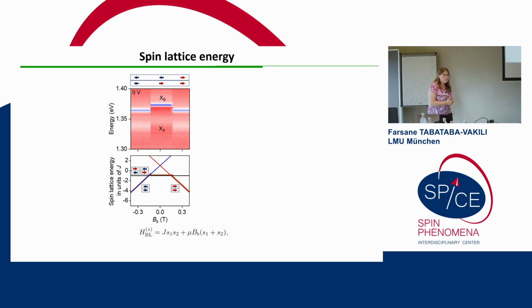And now let's have a look at the spin lattice energy to get a better understanding of when which spin flip occurs. So in the bilayer, the situation is relatively simple. We have two antiferromagnetic states which are energetically degenerate and two ferromagnetic states. If we now start off at a negative magnetic field and increase the magnetic field, we start off in the ferromagnetic state, we continue along this curve. At some point, we cross these antiferromagnetic states. We need a little bit of extra energy to flip the spins. This is where the hysteresis comes in. Then we're in the antiferromagnetic state, cross the other ferromagnetic state, a bit of extra energy, flip the spins.